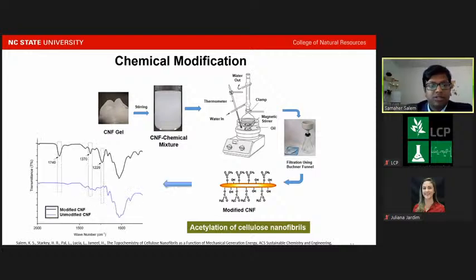Further, the modification was confirmed by doing FTIR, where the modified nanocellulose showed the appearance of new peaks around 1740, 1370, and 1229, which are the characteristic peaks of the acetyl group, and thus it confirms the addition and attachment of the acetyl group onto the nanocellulose surface.